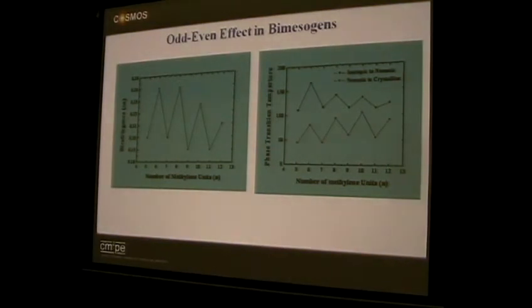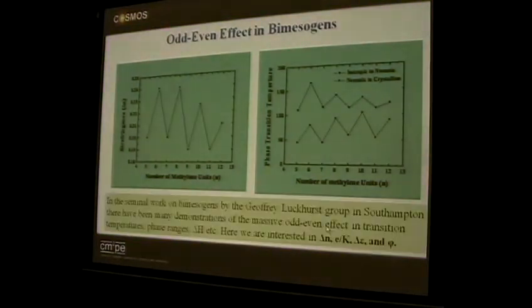And go back to a little bit of chemistry, a little bit of physics. As you change the methylene spacers, you change the birefringence of your material. Just by adding one CH2, taking one away, or adding an extra one on, you generate large birefringence effects. And the transition temperatures equally will change by 60 degrees. So just adding one CH2 group, one methylene spacer unit, changes your phase transition by about 60 degrees. And that's what allows you to have very wide temperature ranges in mixtures.